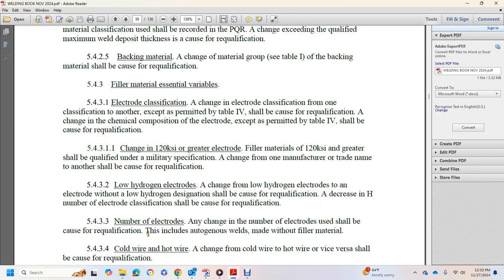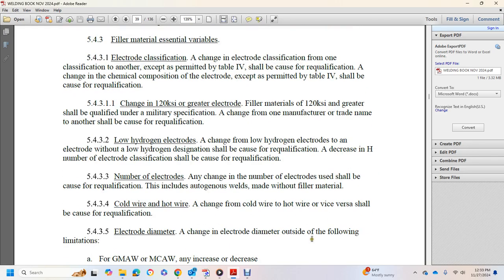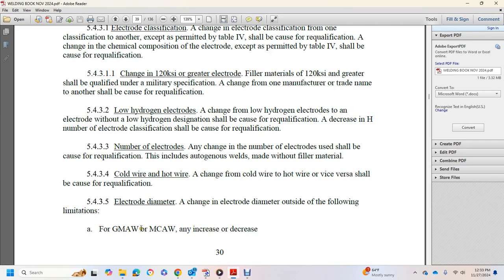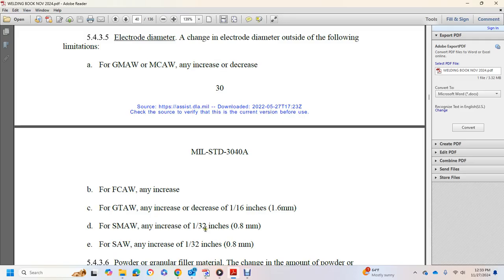For the welds made with the filler metal material with the cold wire, hot wire change, cold wire to hot wire or vice versa, because of the requalification. Electrode diameter: the change of electrode diameter outside of the following limitation. Gas metal arc welding increase or decrease, flux core welding increase, gas tungsten arc welding increase or decrease 1/16 of an inch, shielded metal arc welding subject to the 1/32 of an inch, and submerged arc welding increase to the 1/32 of an inch.